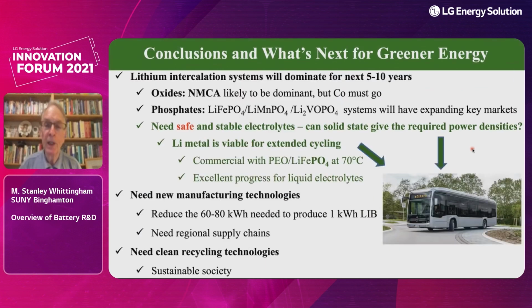So let me finish by making a few comments. It's my belief that lithium intercalation systems will dominate for the next 5 to 10 years. We heard in the last talk possibilities for lithium sulfur, and the Battery 500 project is also looking at sulfur. But that's probably at least 5 years away, even for the smallest systems. Amongst the cathodes, the NMCA is probably going to be dominant, but cobalt has to go. I think it must go essentially to 0 if we can do it. And I think Jeff Dahn has shown he doesn't believe cobalt is essential.